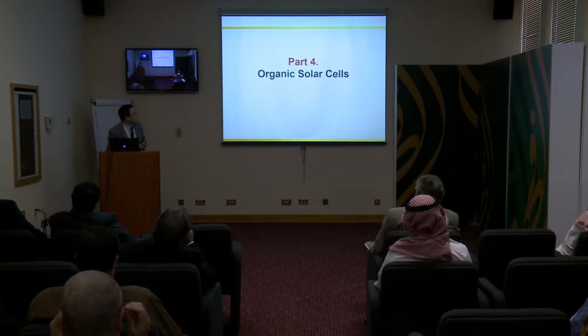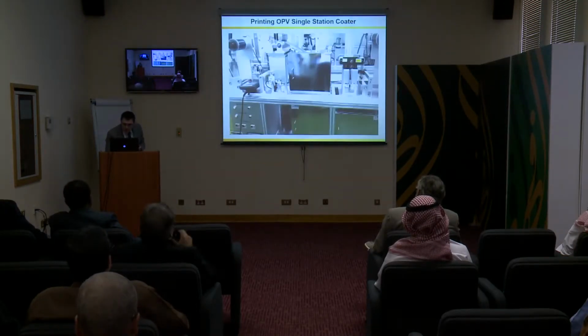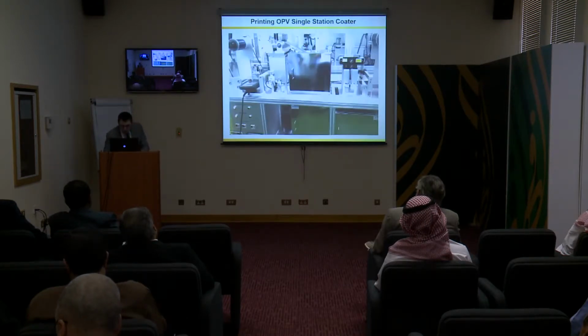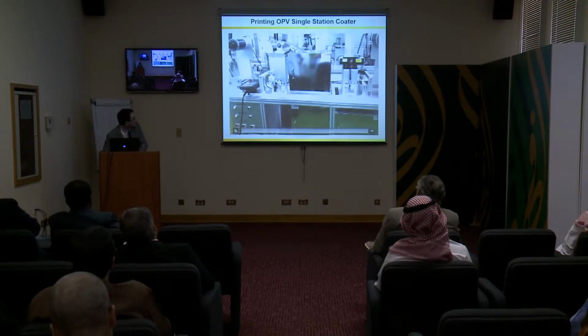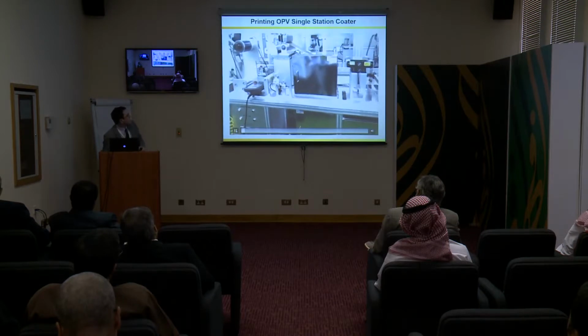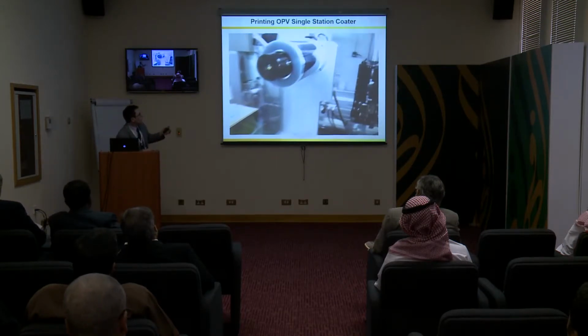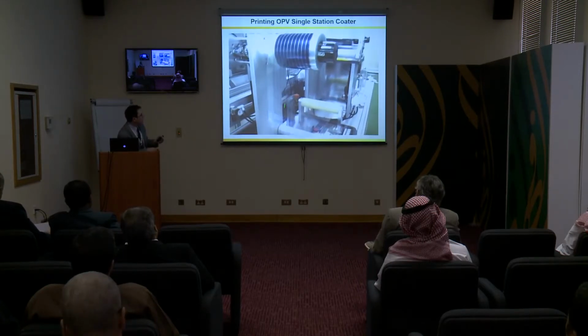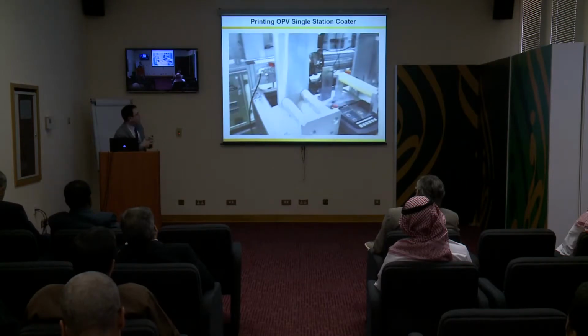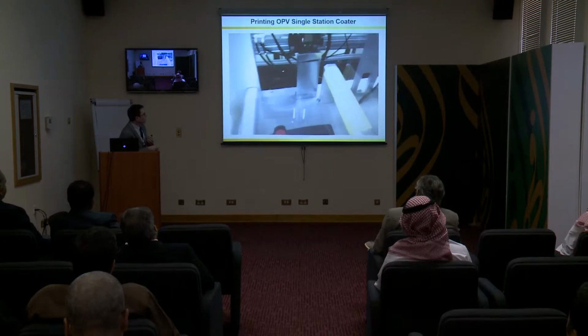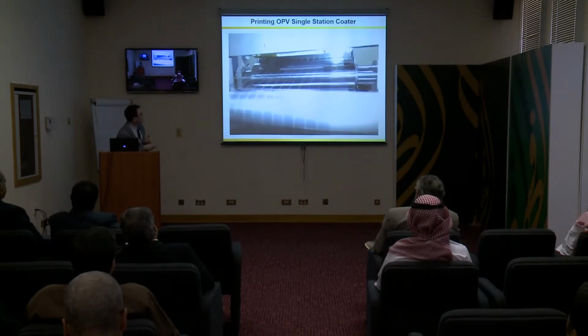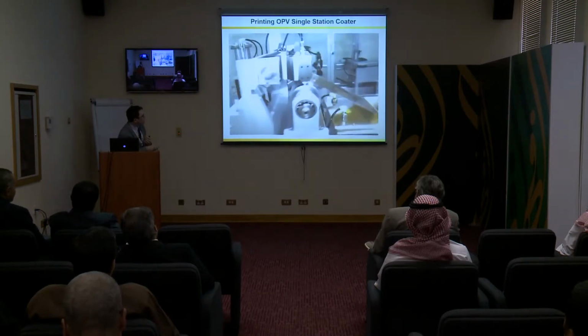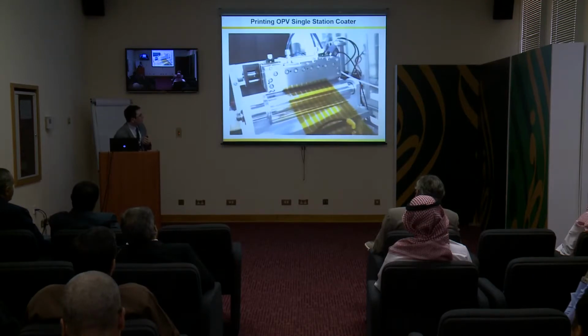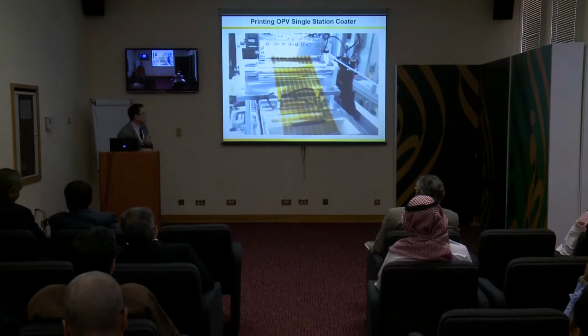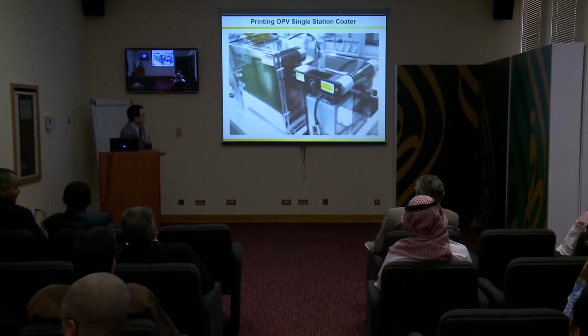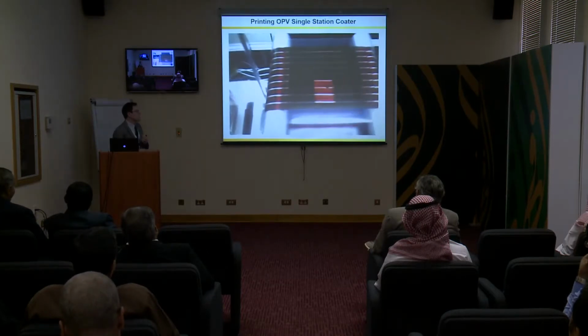The last part, I want to talk a little bit about some of the work we've been doing on solar cells. For those of you who are a little less familiar, the ideal process, I don't know if it's going to work, that we took is simply to start with a plastic which can then be coated with your bulk heterojunction photoactive layer on a simple roll. Once the coating has occurred, it goes into the heating systems, starts drying, and eventually will dry completely. This is a simple P3HT based blend which should come out purple after it's completely dried. Okay, so the process is very, very simple.